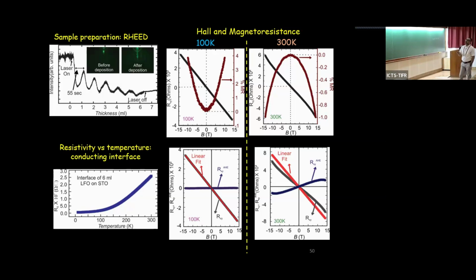If you look at the magnetoresistance and Hall data, the right-hand side corresponds to the magnetoresistance, and the left-hand side corresponds to the Hall. And this is the zero of this axis. You see a positive magnetoresistance, and it's a completely linear Hall. We fit a linear fitting, and the extra part of the Hall, which could be an anomalous Hall, is 0. But when you go to 300 Kelvin, this magnetoresistance becomes negative magnetoresistance, which typically we don't expect.